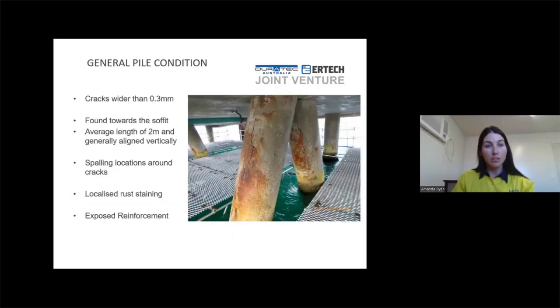So the pile condition, in general, the cracks noted were a lot wider than 0.3 millimeter, which is quite wide for a crack. They like to say anything above 0.2 should be remediated or repaired. So our cracks are quite large. They were found towards the soffit. Average length was about 2 meters. Spalling locations were relatively all around the cracks, and localized rust stains, as you can see from the photos, were around the cracks as well. And in some areas, there's even exposed reinforcement.